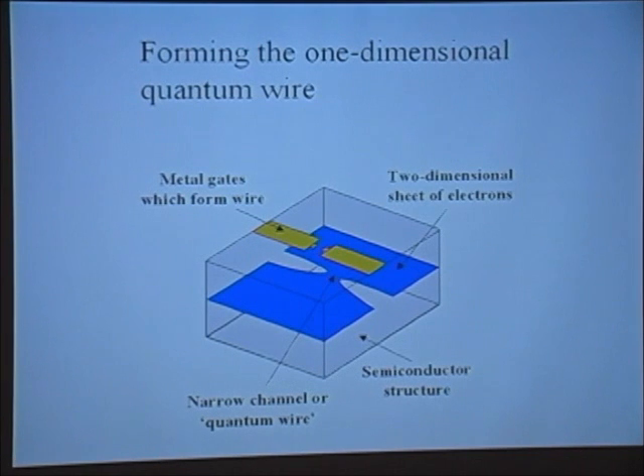So this is how one makes such a structure in a semiconductor. We start off with a 2-dimensional electron gas formed at the interface of gallium arsenide and aluminium gallium arsenide, as we've just discussed. We form, this is the most simple structure, two metal gates on the surface. If we apply a negative voltage to these two gates, we deplete the electron gas underneath. We end up with a little bit of electron gas there, a narrow constriction, which can form a wire. We can basically squeeze it until we just get rid of it completely. To give an example, we can squeeze it typically from about 1,000 angstroms wide down to nothing, more or less.